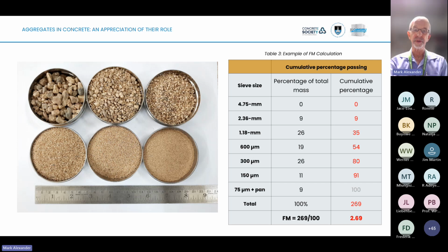And here's an example of a fineness modulus calculation. You take the cumulative percentage passing the standard sieve sizes, and in fact, you can do this for stone as well, and cut off at the 150 micron. You add all of those numbers together, divide them by 100, and there you get the number. It's a fairly crude measure, as you can see. Those gradings could vary a lot and still give you the same number at the bottom. But it's a number we use, and it's useful because it does give us a measure of the average particle size in fineness modulus units.